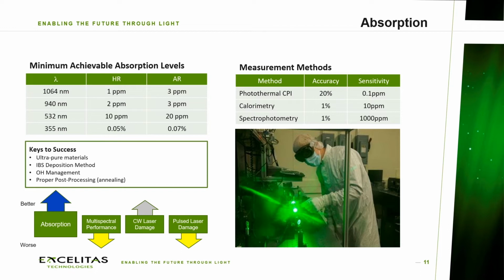We have a preferred method for this level of absorption, which is called photothermal common path interferometry. It's not the most accurate method, but it's highly sensitive. So if we're trying to measure absorption levels that are around 1 part per million, it really is the method of choice. If the absorption level is expected to be higher, there are other methods that are more accurate.